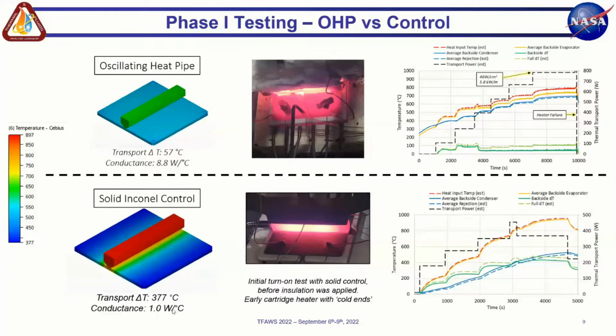So here we simulated, expected about a 9x improvement in conductance, and we actually saw very close to that. This is a prediction of simulations run before testing, and the experimental work actually showed a very similar improvement, about an order of magnitude better performance thermally than the solid Inconel plate. So coming from effective thermal conductivity of the base envelope, on the order of 20 watts per K, up to an aluminum or better type number, but of course with much higher service temperature than you would see from aluminum or copper.